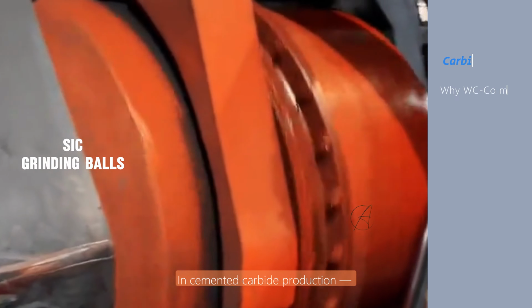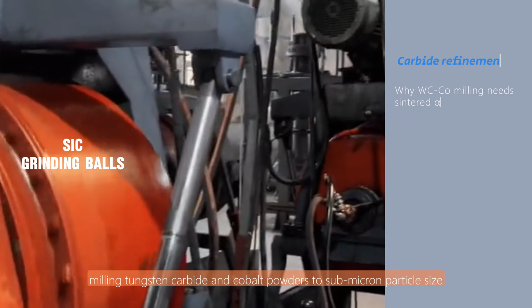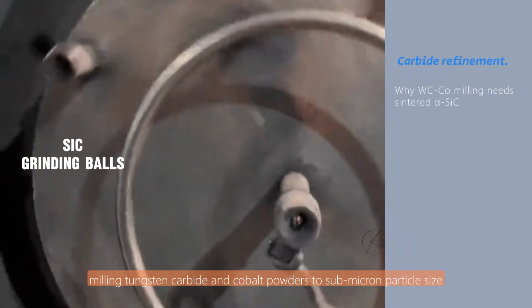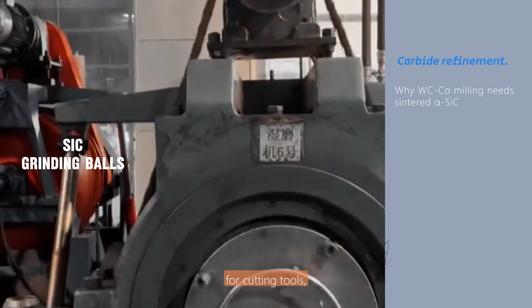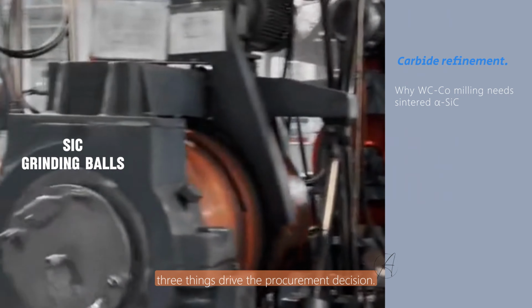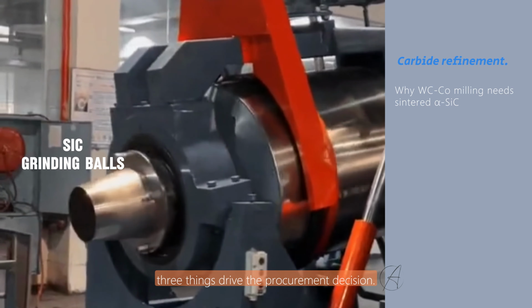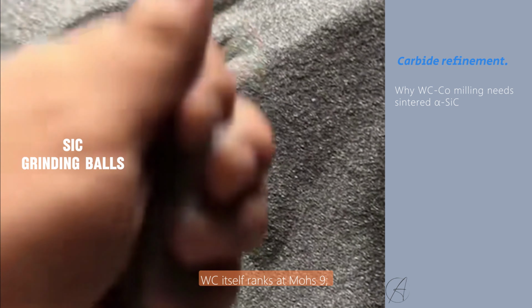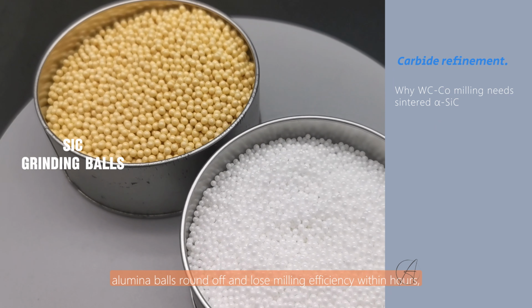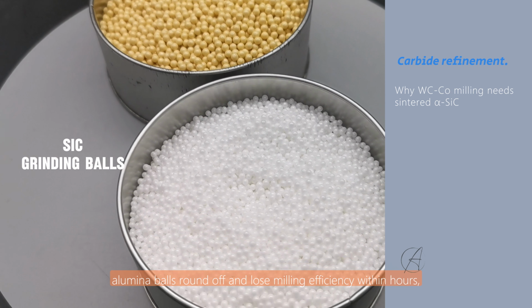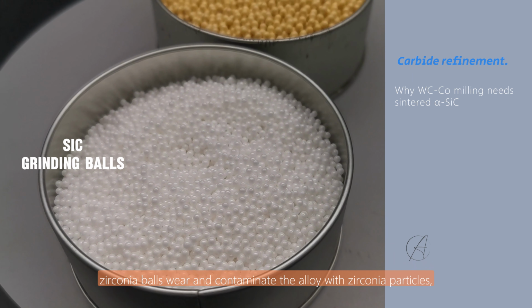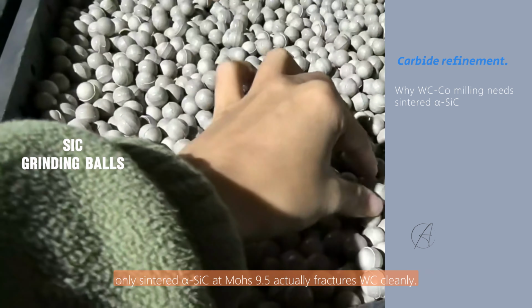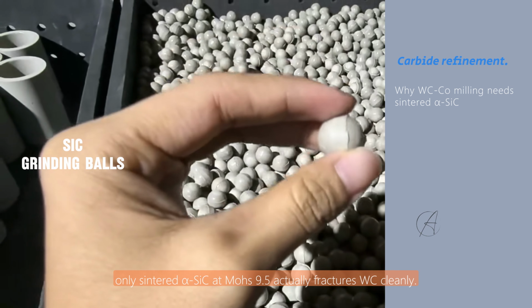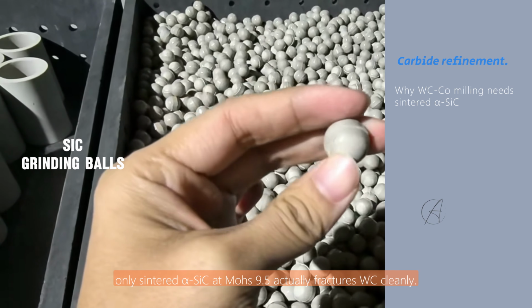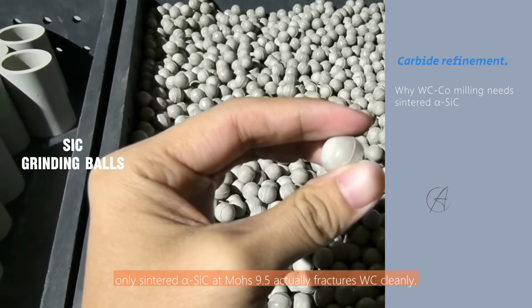In cemented carbide production, milling tungsten carbide and cobalt powders to submicron particle size for cutting tools, drill bits, and wear parts, three things drive the procurement decision. First, hardness gap. Tungsten carbide itself ranks at Mohs 9. Alumina balls round off and lose milling efficiency within hours. Zirconia balls wear and contaminate the alloy with zirconia particles. Only sintered alpha silicon carbide at Mohs 9.5 actually fractures tungsten carbide cleanly.